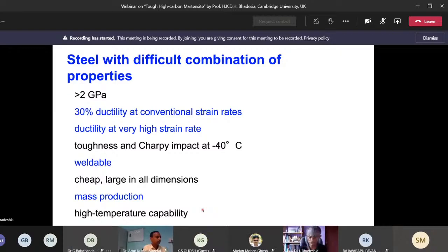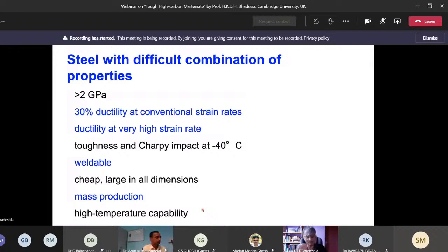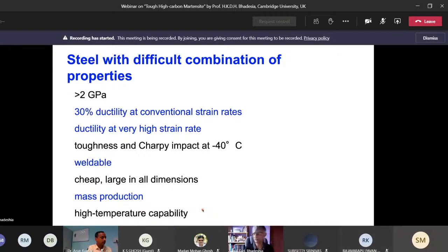Okay, so we want to create this very difficult set of properties in order to make a steel which has a strength of 2 gigapascals, yet is weldable, and you can make it in huge quantities. It has toughness and many other properties. So how can we do this? Well, we are going to design the steel as fully martensitic immediately after it is rolled, right? So there's no further heat treatment after that. And the only way we can achieve this combination of properties is to make the austenite grain size extremely small.